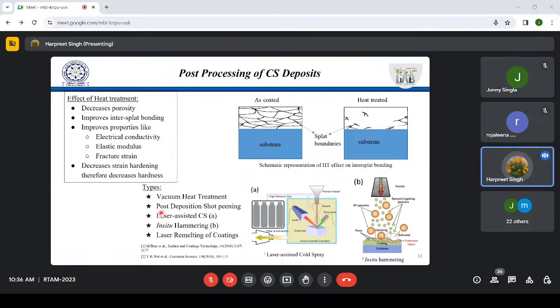So this approach is being used, but there is some other interesting work people have done. Some people are doing stress relaxation by post deposition shot peening also, right? Then laser assisted cold spray is also being tried, to get the desired ductility in the materials. In situ hammering is another interesting application, where people are using slightly bigger hard particles, which are just giving the hammering effect, and they're not getting deposited. Rather, they'll come, they'll hammer. It's like in situ peening kind of thing, right? So this hammering will increase the adhesion between the layers. Cohesion is improved by this, but then they'll rebound and go back, right?